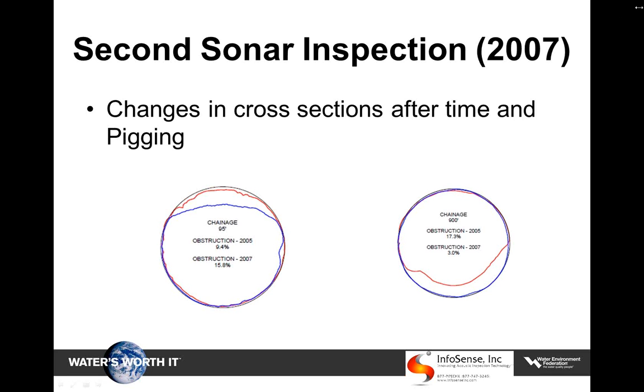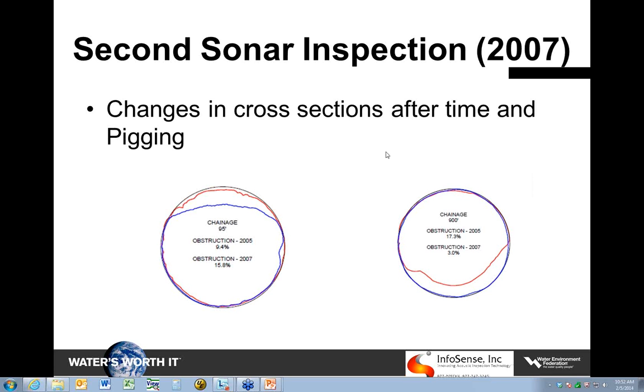Once again, the second inspection did show some changes in the cross sections. In this case, at 95 feet, the image on the left, we actually showed more obstruction in 2007 than we had in 2005. Once again, this was after the pigging. And then at 900 feet, the image on the right shows that we actually had less obstruction in 2007 than we did in 2005.